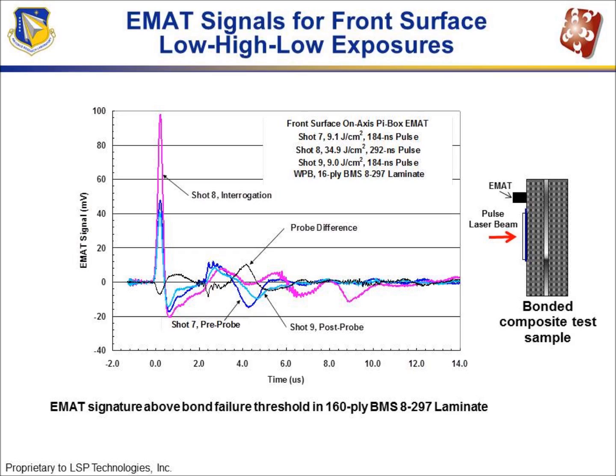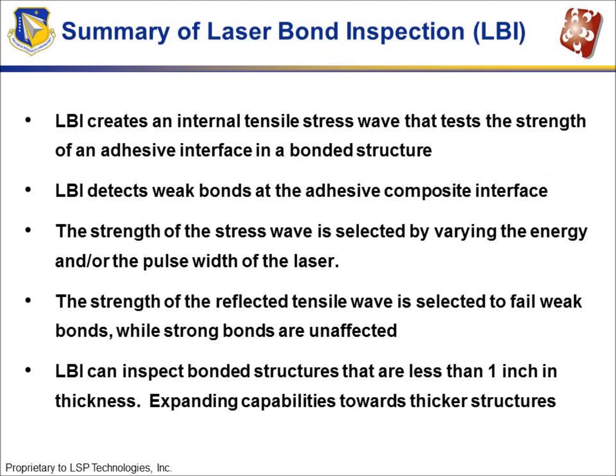This is similar to the signal that we covered earlier with the VISAR and the simulation that Boeing put together. Basically, we have a compressive wave, then the tensile, then this series of tensile and compressive waves. To summarize, laser bond inspection creates an internal tensile stress wave that tests the strength of an adhesive interface of a bonded structure. Laser bond inspection detects weak bonds at the adhesive composite interface.